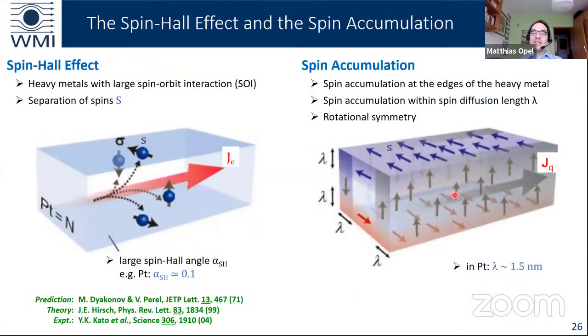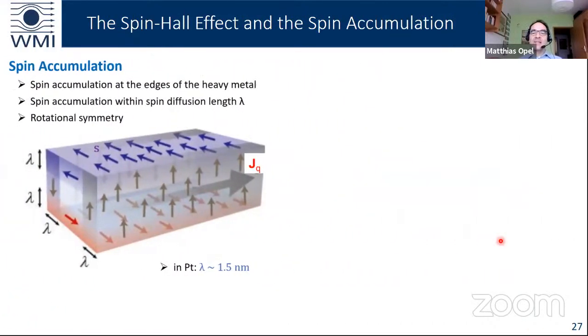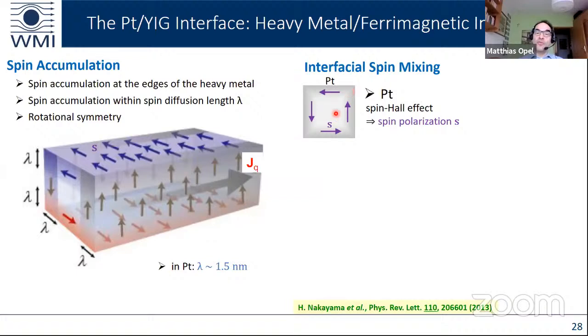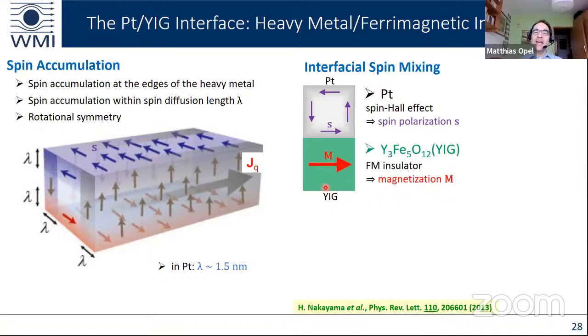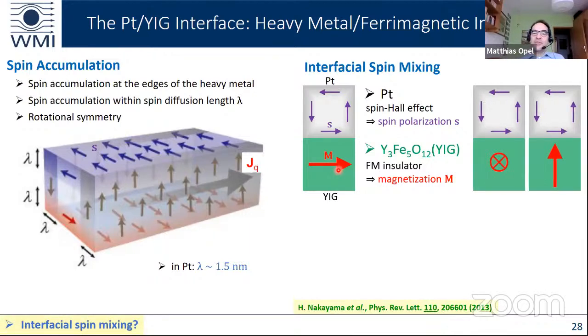So the spin Hall effect leads to a spin accumulation at the edges of the platinum, and this spin accumulation shows a rotational symmetry. And when we now put some magnetically ordered material, so this is the view from the front, spin left at the top, spin right at the bottom, like YIG in contact with the platinum at the bottom, then we have an interface here. And right next to the interface is the spin polarization of the conduction electrons in platinum and the magnetization of the YIG. So in principle, there are three principally different geometries with regard to the magnetization of the YIG. The magnetization of the YIG can point to the right, it can point into the blackboard, or it can point to the top.